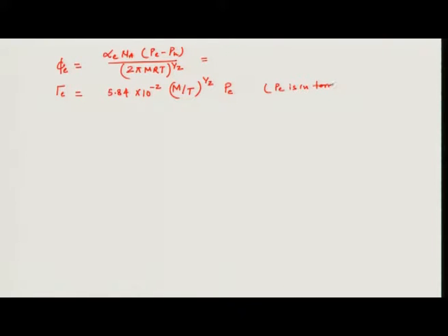Okay. And this P E is the vapor pressure of the source being deposited or evaporated at temperature T. M is the molecular weight, and this gives you an idea how much mass, this is in grams per centimeter square per second. Okay. How many grams of the material per unit area of the source per second is going